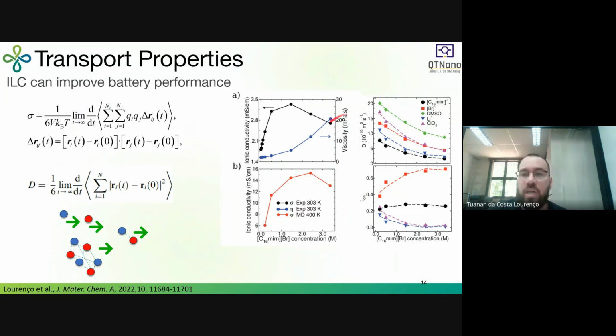So in general, for simple liquids like water or any pure solvent, you expect that when you see this increase here, you are going to see the decrease here. So the viscosity is directly related to the mass transport in the system. Although the way that we measure viscosity in MD simulations, we are not measuring the mass transport. We are working with the pressure tensor of the box, similar to what you do in DFT calculations, but you are totally correct. Viscosity is related to the mass transport.